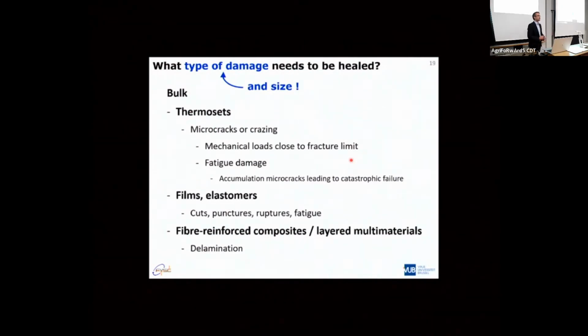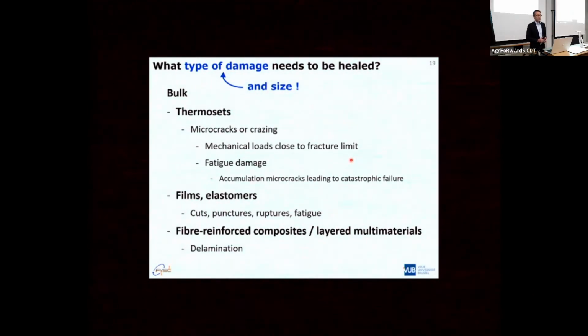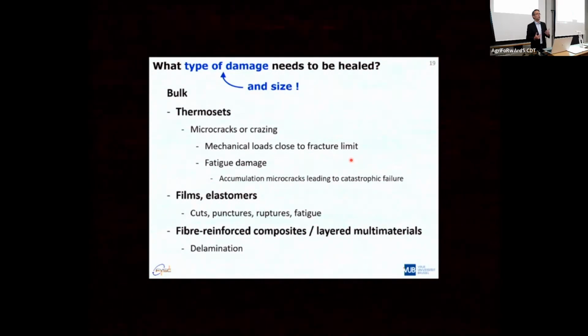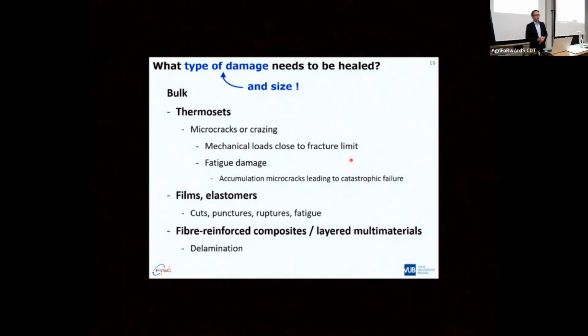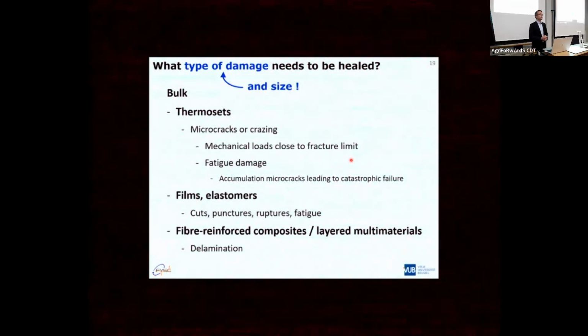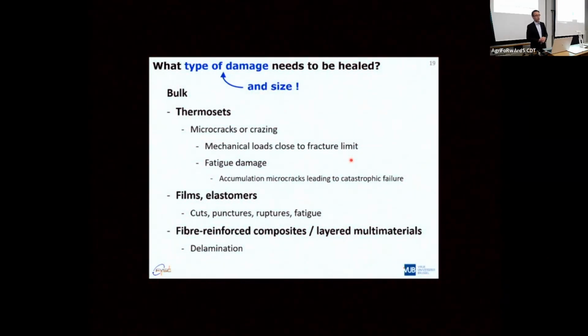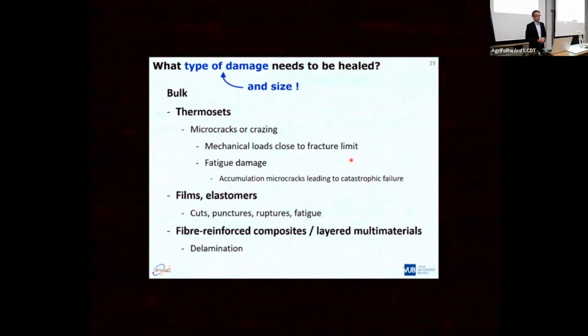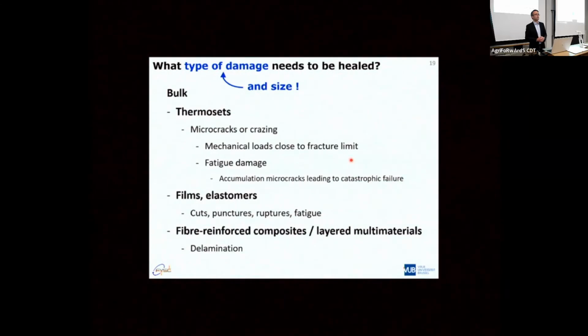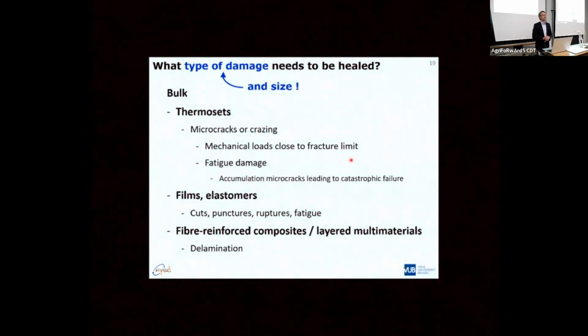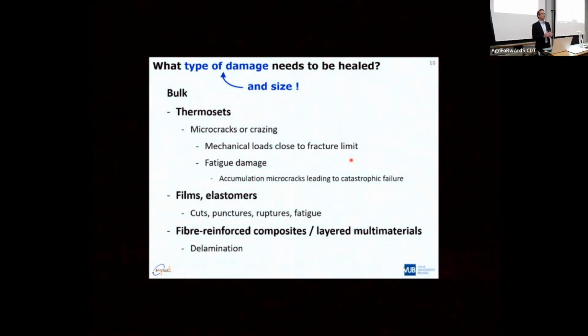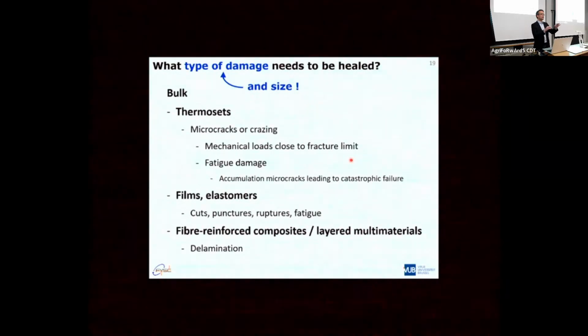Now, from a robotics viewpoint, you might be more interested actually in bulk properties. There, I just made, let's say, a kind of an overview of a few different polymer systems that you could study. Of course, if you go to thermosets, and I mean glassy thermosets at room temperature or at application temperature, then microcracks and crazing. So the cracks that you see appearing if you have a polystyrene or a plexiglass box and you push too hard on it, it will typically not shatter into pieces immediately, but first you will have these cracks developing in the material.